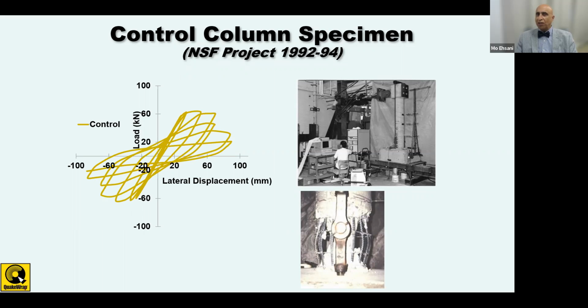These were built similar to those old details, with large spacing between the ties. As you would expect, shortly into the test, you would start damaging the base of this column. That's where the plastic hinge is being formed, with a lot of concrete crushing. And as you can see in the load deflection curve, after a couple of cycles, the more you push, the column cannot take any more load, and the loads start to drop. So that is not a good behavior.